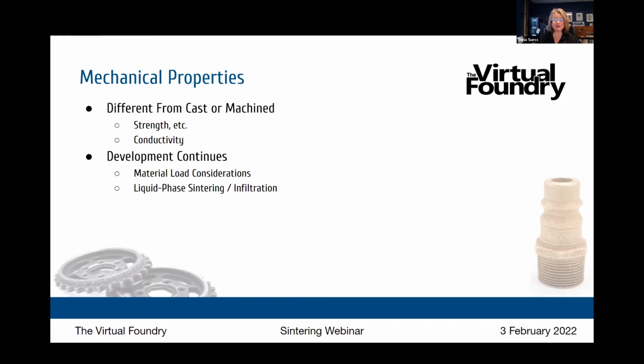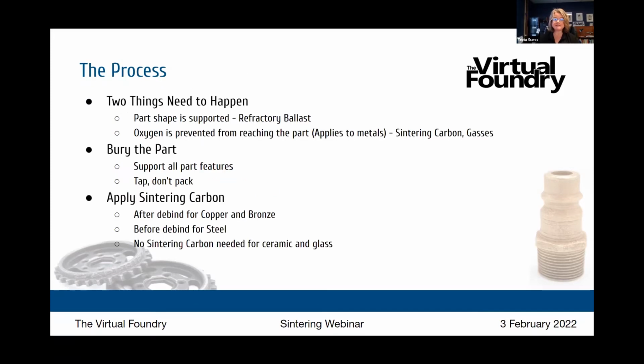All right, let's get on to the process. So when you're thinking about debinding and sintering filament, two things need to happen. The first is that the part shape is supported, and the second is that oxygen is prevented from reaching the part, and I'm talking about metals in that case. So we solve the part shape problem by using a refractory ballast, and we solve the oxygen problem by using sintering carbon. Some people like to use a gas fill kiln. In that case, that takes the place of the sintering carbon, but in an open atmosphere kiln, sintering carbon will prevent that oxygen from reaching your part.